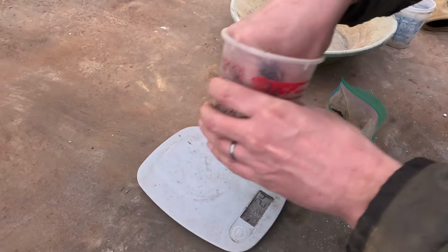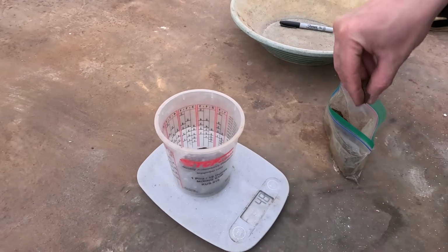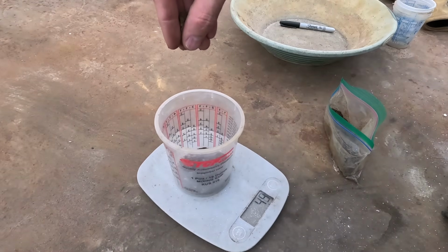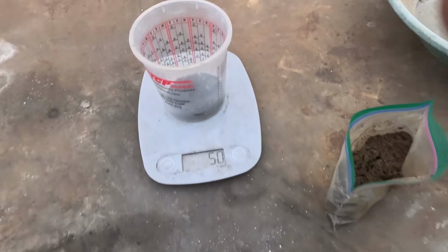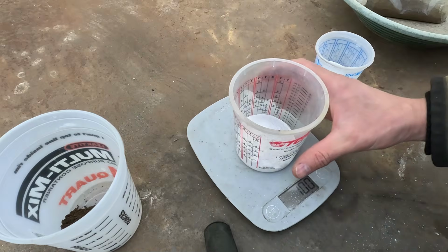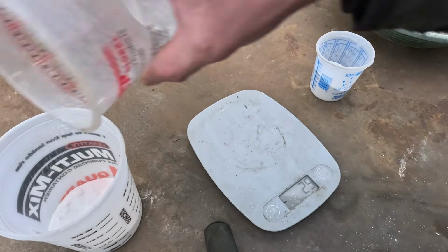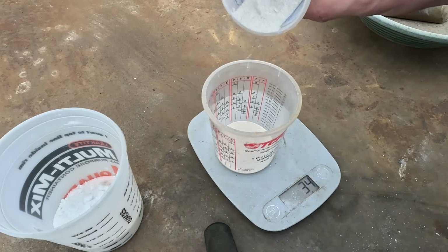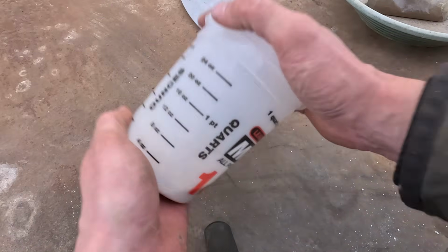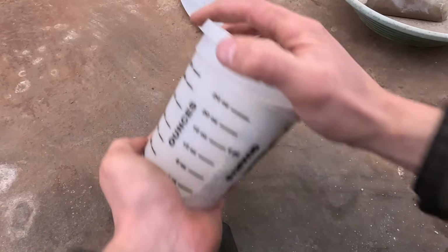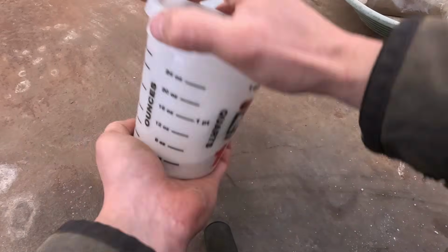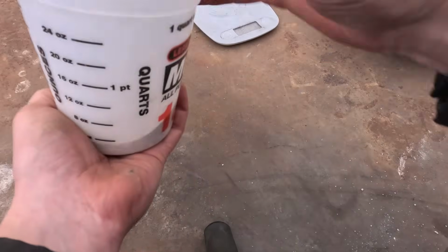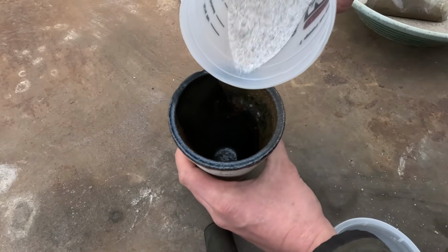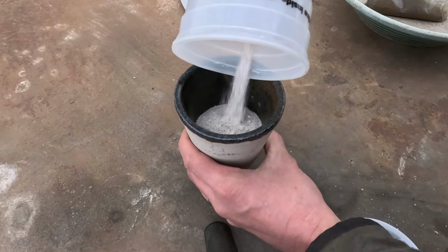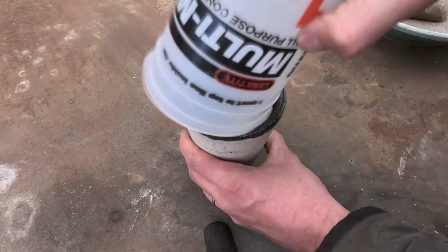What I'm going to do is cut the amount of concentrates in half and use the same amount of flux. So I'll use 50 grams of concentrates and still use 100 grams of soda ash, 65 grams of borax, etc. We'll mix that all up and try it again, with the idea being that we used up, for lack of a better term, the soda ash in the first smelt, and so having less concentrates, hopefully we will have enough to absorb all the matte.